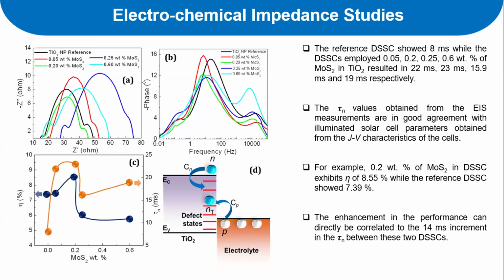In order to counter that, if we put the 2D layered material on top of the titanium dioxide, then it can efficiently absorb and then inject the photogenerated electron into the conduction band of the titanium dioxide, and from there it can be collected onto the electrode. So that is what is happening, and the major reason for the enhancement of the performance of the solar cell in this particular case is the enhanced charge carrier lifetime in the conduction band of the electron acceptor, which gives more opportunity for the electrode to collect those electrons.